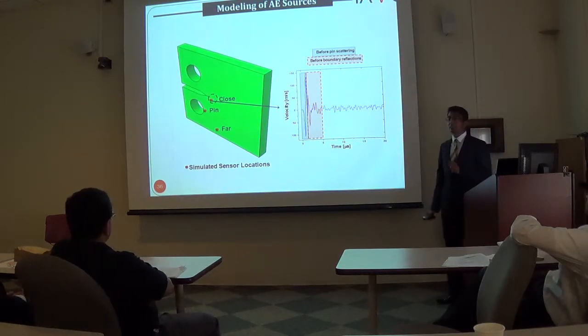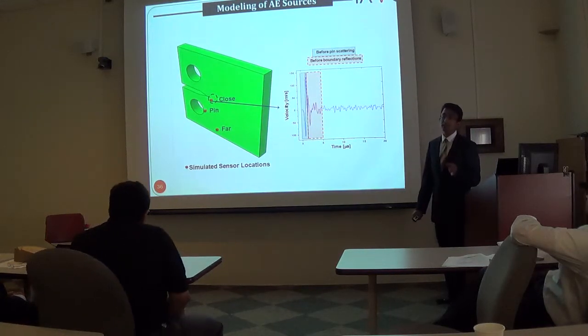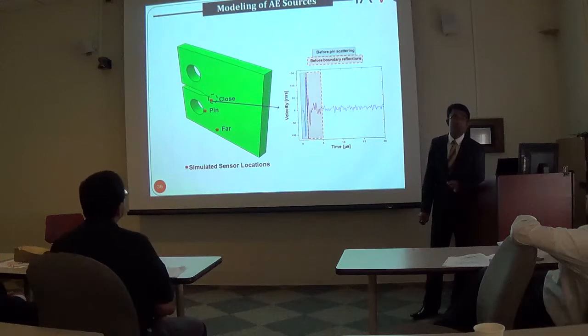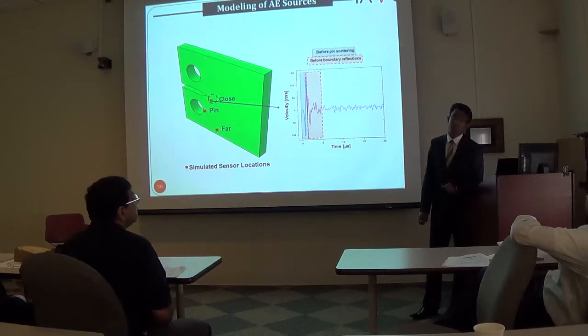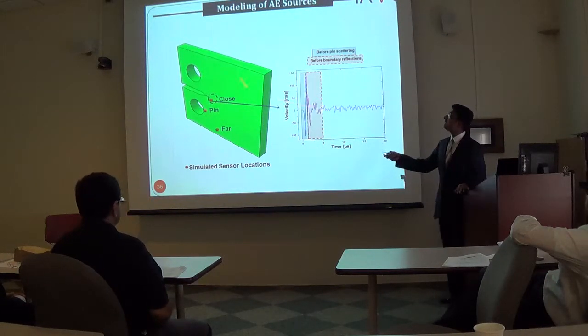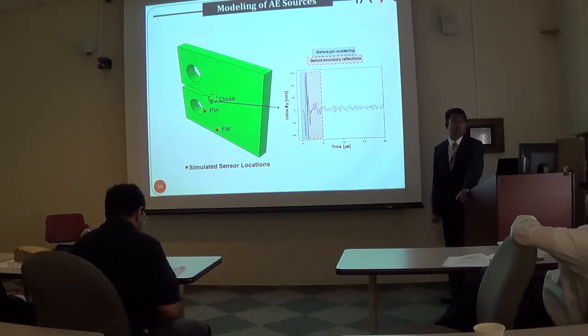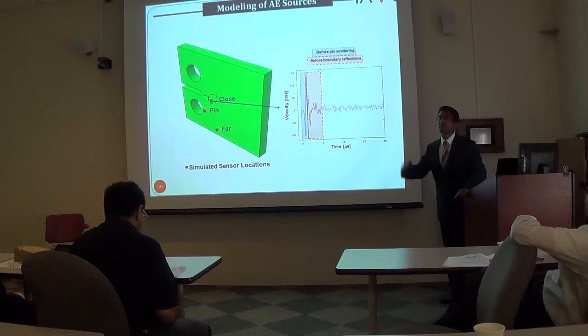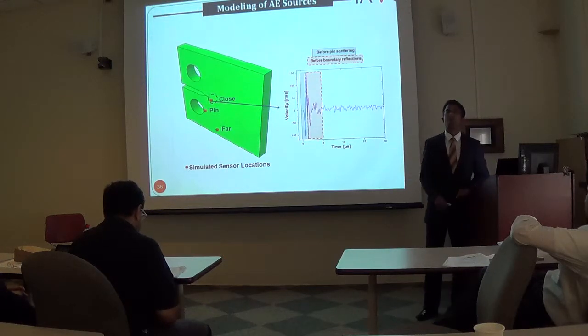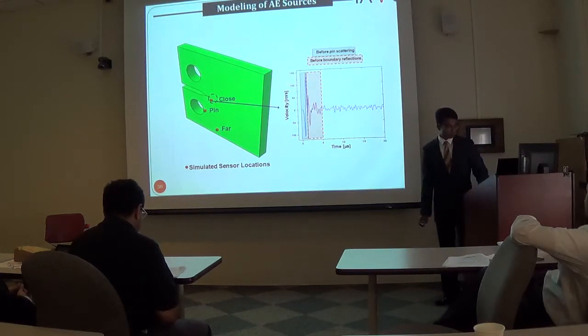Thus, this tells us that utilizing threshold-based analysis or amplitude-based analysis for damage detection might not be very reliable, because these features clearly change as the waves interact with the structural geometry or the features of the material. And so we need to shift from these kinds of threshold-based analysis to more advanced AE analysis.